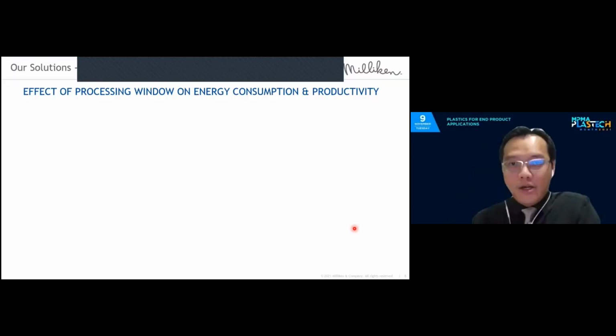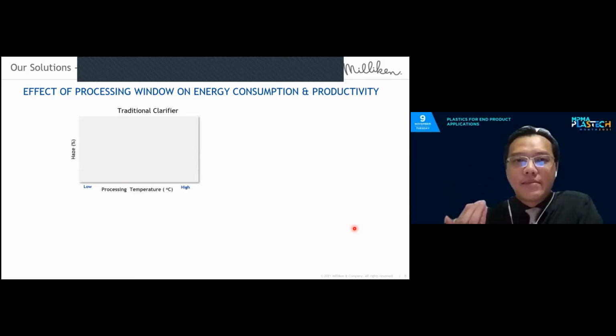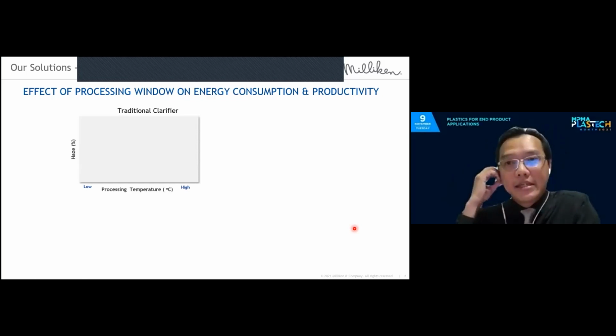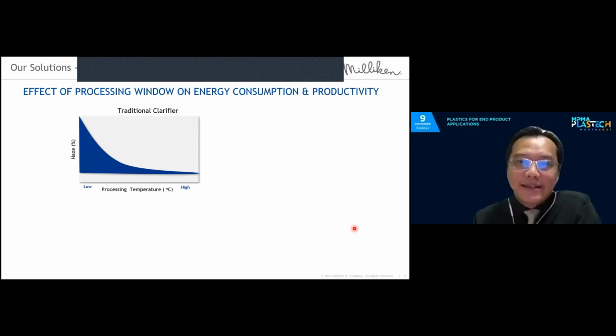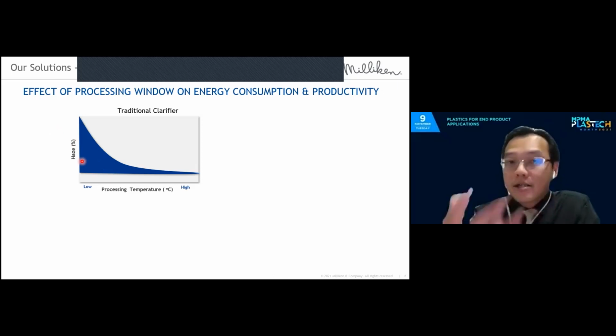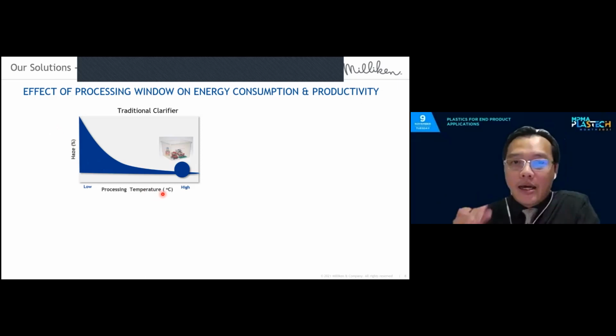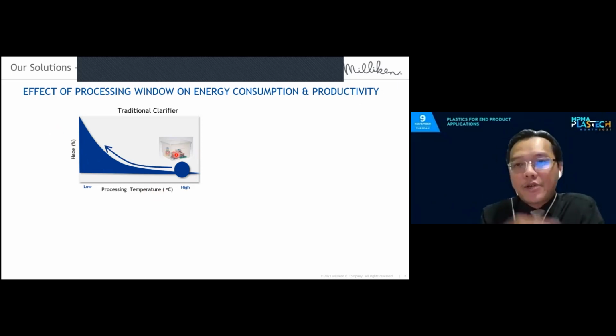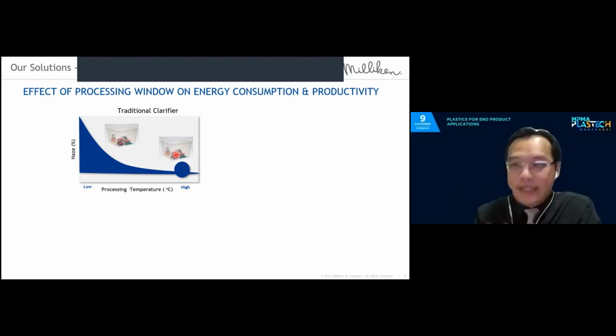Right. So I hope the video was clear enough, but let me quickly go through the technical fundamentals on how NX8000, the clarifier for polypropylene, enables this productivity increase. So traditional clarifier before NX8000 was introduced to the market, maybe 10, 12 years ago, there was a dependency of haze, which is the optical performance, the transparency, versus the processing temperature or the injection melt temperature. The traditional clarifiers have the drawback that they need high temperature to be able to work properly and therefore deliver the optical performance. If you try to reduce the processing temperature, reduce the heating to your extruder, then the parts will turn less and less transparent, and it does not meet the requirement, because the requirement of a clarified random copolymer is for the optical performance.